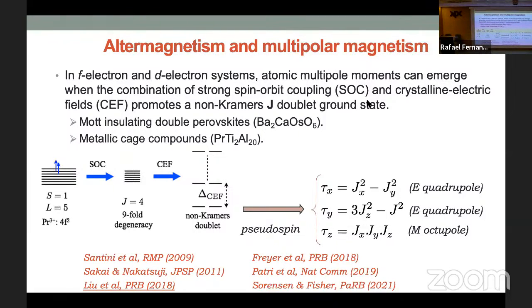So let me just walk you through that. You start with praseodymium 3+, plus spin 1, L equals 5. In the presence of spin-orbit coupling, you get a J equals 4, which has a ninefold degeneracy. Now you put it in the crystal, it splits into these levels. And the ground state here is a non-Kramers doublet. What it means is that in this case here it is a cubic system. It belongs to a two-dimensional irreducible representation. So you can describe a pseudospin. Again, I need an atomic limit, in the limit of very large U, okay, to explain that. So the pseudospin here, again, up and down are no longer spin up and spin down.